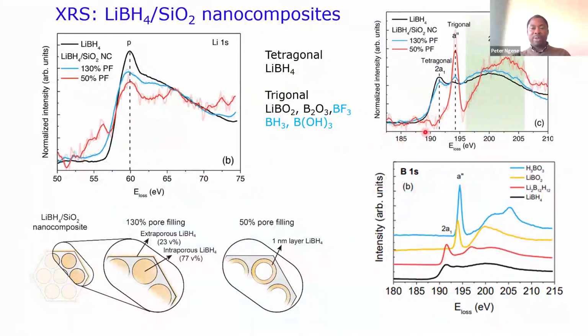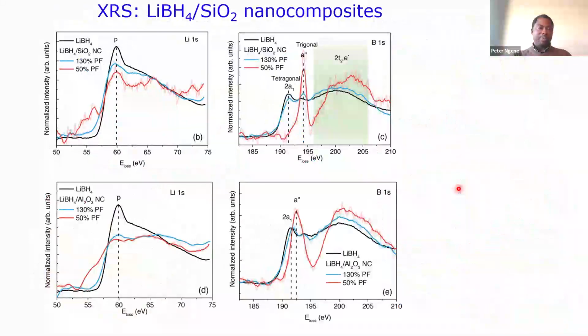But basically, what we do see is that at the interface, we do have trigonal boron instead of tetragonal boron, which we think is something that looks like this, because it's not LiBO2, because LiBO2 is not conductive, neither is this conductive. Okay, so this is based on this fingerprinting.